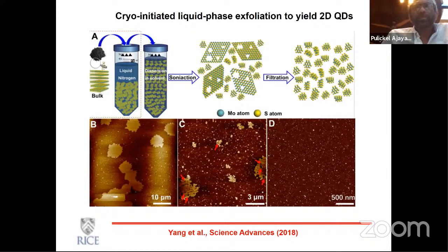One recent work that we showed, where we could get very facile breakup of these layers, is by simply doing a pre-treatment with liquid nitrogen. So if you dump some of these layers into liquid nitrogen, they stiffen up. And then when you do a sonication-based breakup, you get much more uniform quantum dots. So this is just another trick that one could use to get a higher yield of quantum dots and more uniform quantum dots. Maybe you could also do cryomilling, which would give you a similar kind of result, but this was a simpler way of doing this.